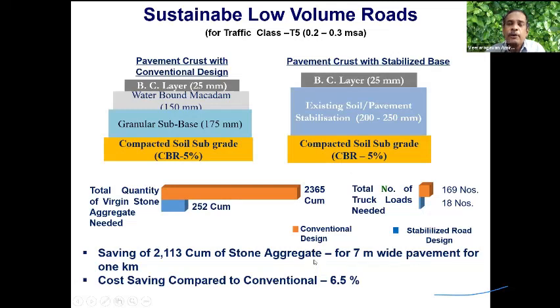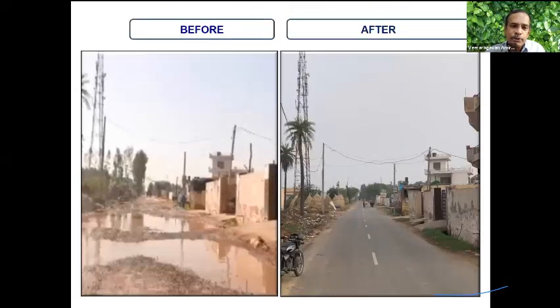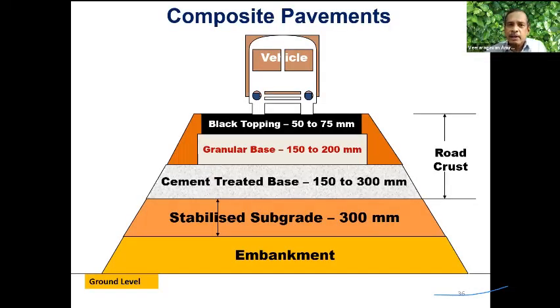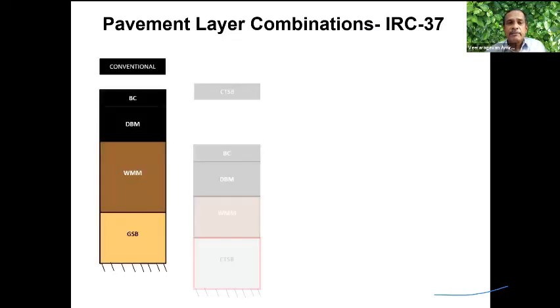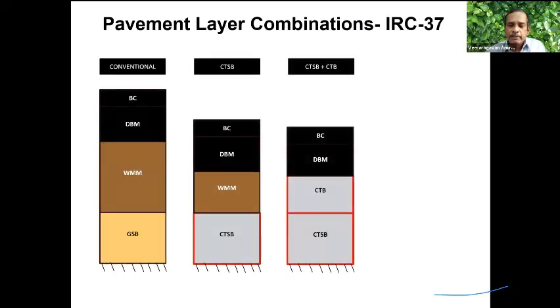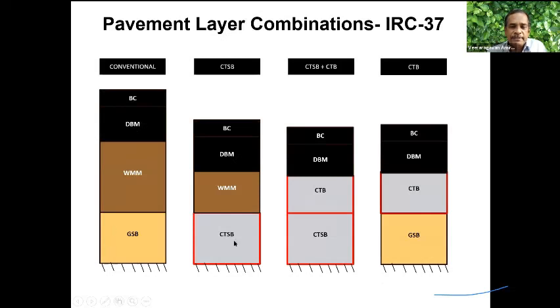Therefore, if you talk about sustainable practices in civil engineering, in road construction, simple solution is adopt stabilized subgrade, stabilized subbase, stabilized base courses. A road which was like this can be made good like this by introducing stabilized pavement layers. Look at the composite pavement or inverted pavement, you will find that I can reduce thickness of bituminous layers to 50 to 75. When you talk about the different designs possible, you'll find that instead of having a granular subbase, I can have a cement-treated subbase. I can have a cement-treated base. I can have a granular subbase and cement-treated base.